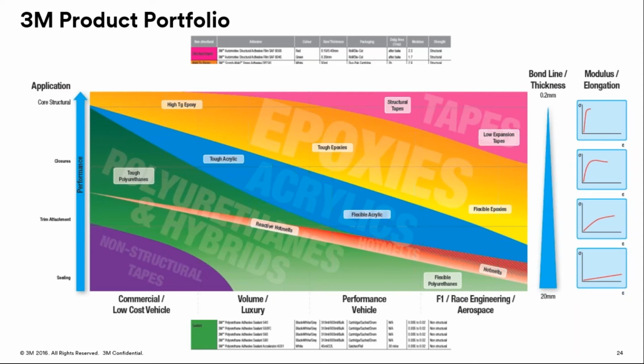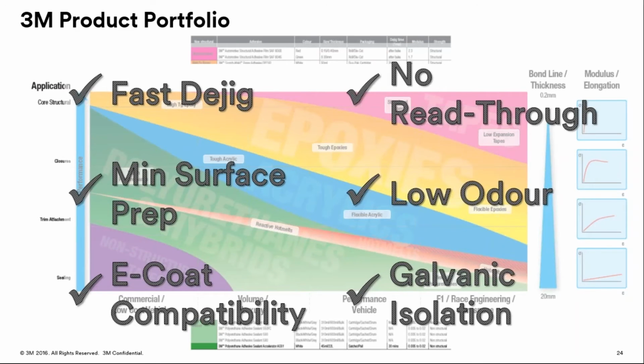But it's not all about mechanical properties. There are processing requirements such as fast dejig. We also demand no read-through, so this is eliminating any kind of bond line read-through onto the A surface of the vehicle. Minimal surface preparation, low odour, compatibility with E-coat, so currently every vehicle will go through 180 degrees for half an hour for the E-coat bake. And also galvanic isolation, and that we need to ensure that these multitude of different materials are not setting up corrosion cells.